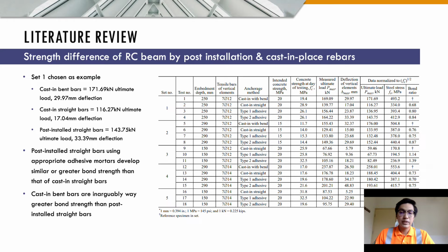The cast-in bent bars was able to take 171.69 kN of ultimate load and 29.97 mm of deflection. The cast-in straight bars was able to take 116.27 kN of ultimate load and 17.04 mm deflection. The post-installed straight bars was able to take 143.75 kN ultimate load and 33.39 mm deflection.